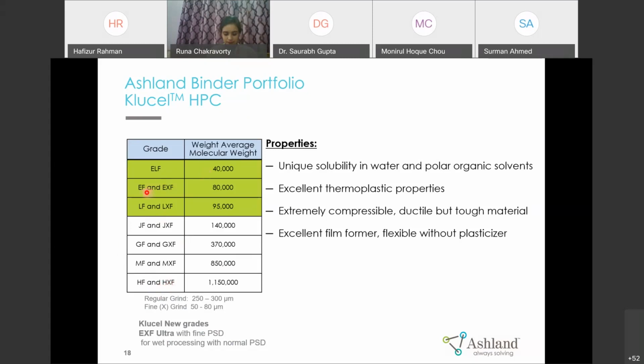Then you may be thinking that we have EF and we also have EXF, which have the same molecular weight. So what is the difference between EF and EXF? Wherever you see X, the X tells us it is the finer particle size grade. You can see the regular grade D50 is from 250 to 300 micron. However, the finer grade D50 is between 50 to 80 micron. And recently, we also launched Klucel EXF Ultra, which is an ultra fine grade having one third the particle size of the finer grade.